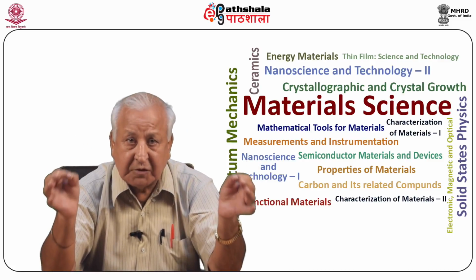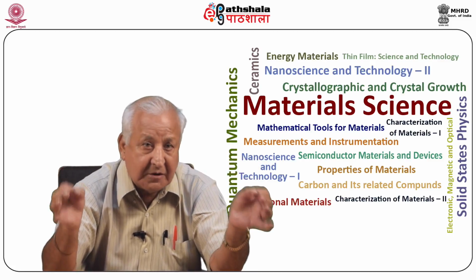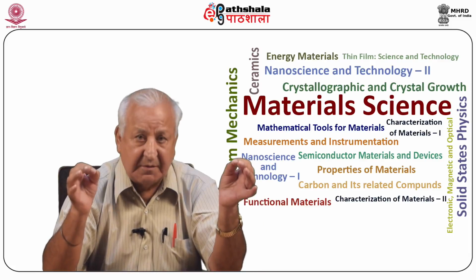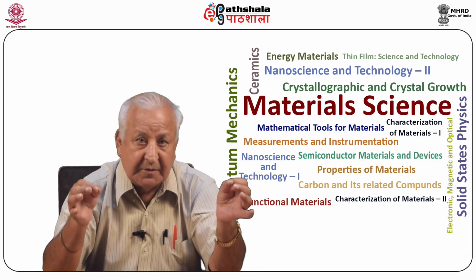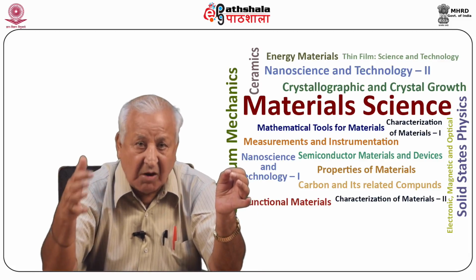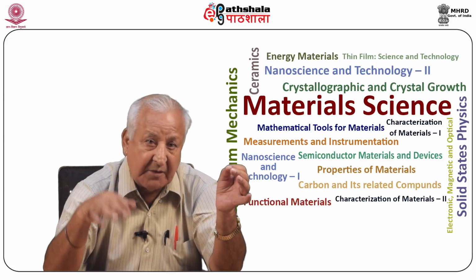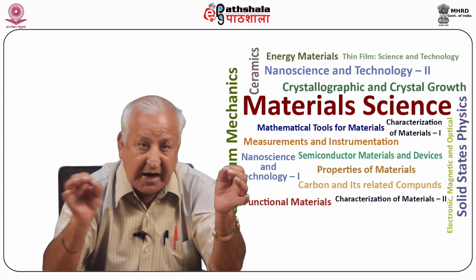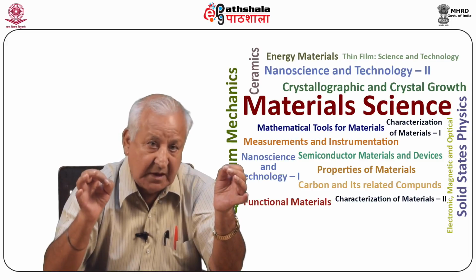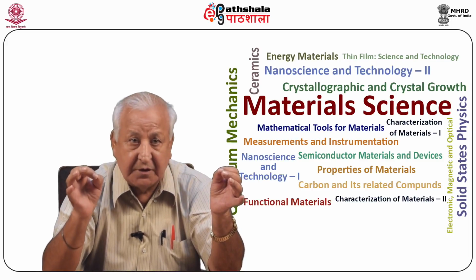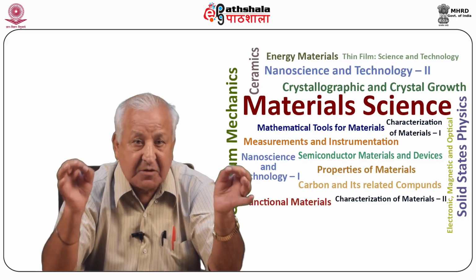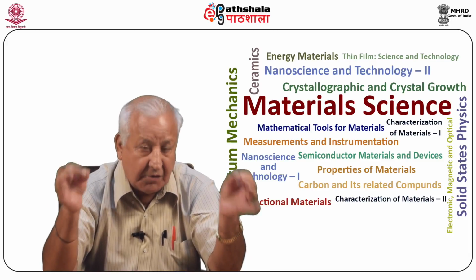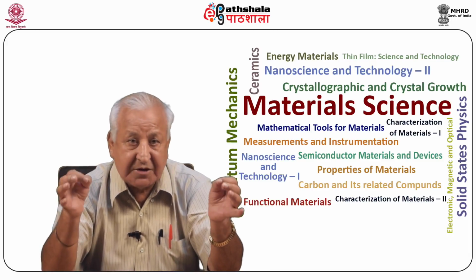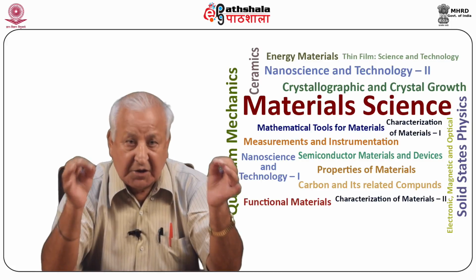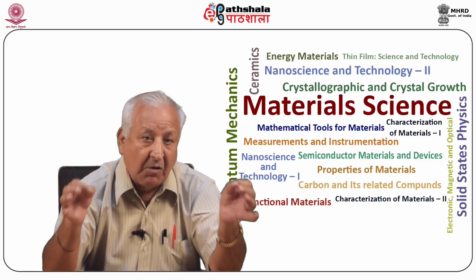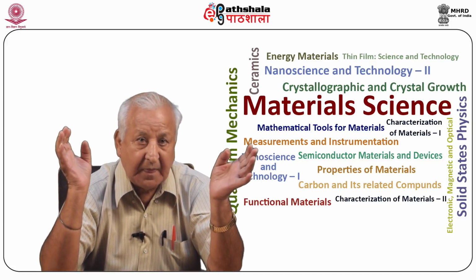To favor growth of crystals on the bottom rather than at the surface of the melt, the top of the crucible is kept 10 degrees centigrade hotter as compared to the temperature of the bottom by adjusting power of the heater. It has to be ensured that the temperature is kept constant, since a sudden drop would cause the production of small crystals rather than the desired few large ones.